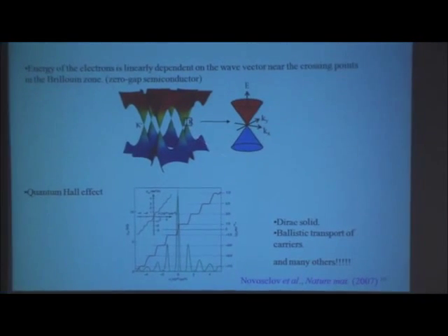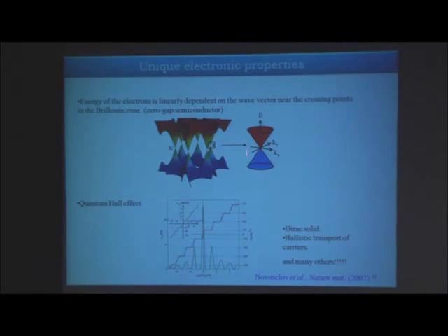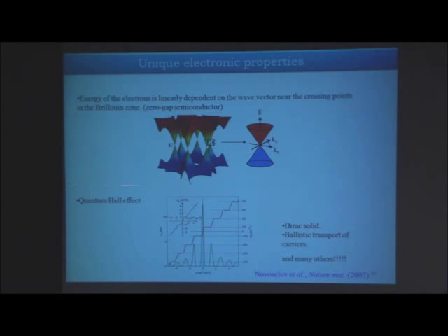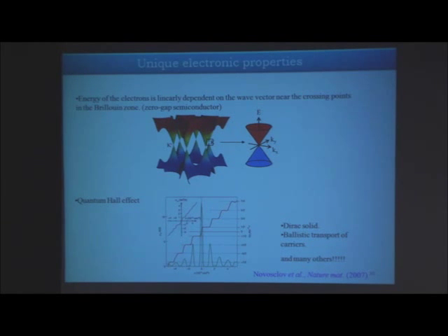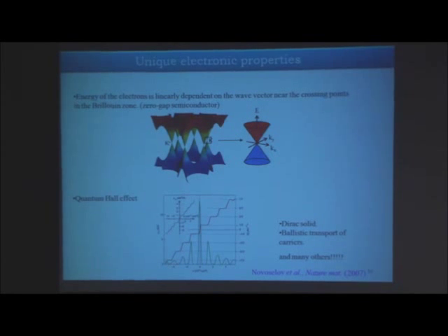So the real problem, however, is that synthesis of this is very difficult. How do you just pick one layer of a graphite crystal and do a study on that? Of course, the reason it became important and why they have given a Nobel Prize is not because a single layer of graphene has been lifted off the crystal, but because of its unusual properties. What these people, Novoselov and Geim, showed is that the energy of the electrons in graphene is linearly dependent on the wave vector near the crossing points of the Brillouin zone. That is one thing. And it also shows ballistic transport of electrons. Ballistic transport of electrons in solids is a very unusual phenomenon, and that happens here. More than that, it also shows the quantum Hall effect at room temperature. Normally, the quantum Hall effect is found at very, very low temperature. It's very difficult to find at room temperature, but this solid shows that. So that's why this solid became famous the minute it was discovered.